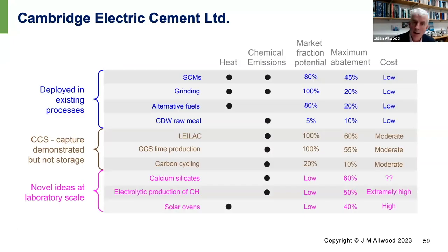There are lots of ideas on the market for reducing the emissions of cement making. Some of them are quite well established, and they have, you can see here, limited total maximum abatement, but a relatively low cost, and they're penetrating at a good rate. So the supplementary cementitious materials is the key thing here, and the industry is moving towards using calcined clays blended with clinker to come up with more cement for less clinker production.